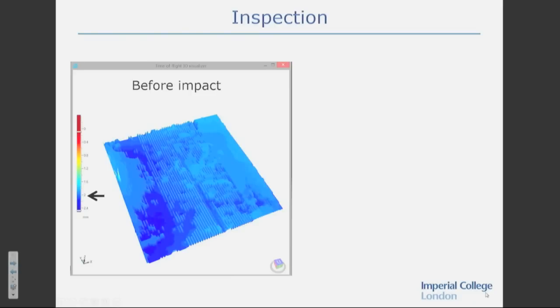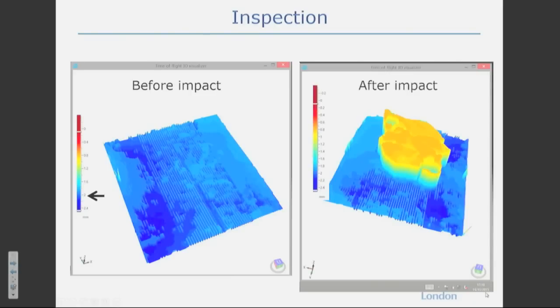And then after the impact, quite a change. You see we've got a sizable orange zone here now, and it's at a depth of about 0.8 millimeters, just before the mid-surface. And from the size here, it's about 20 millimeters across this. So these are the options available to inspect the structure.